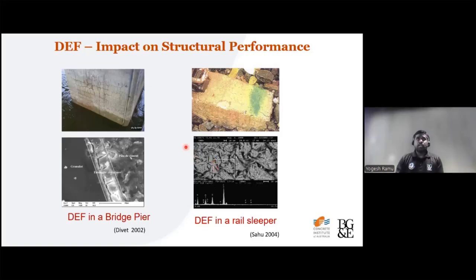Here, you can see any concrete element which is quite large can lead to very high temperature that can potentially decompose the ettringite formation, and so can result in DEF. So I purposely picked two examples, one from in-situ and one from precast concrete. You have to be mindful in both, not just in precast concrete.